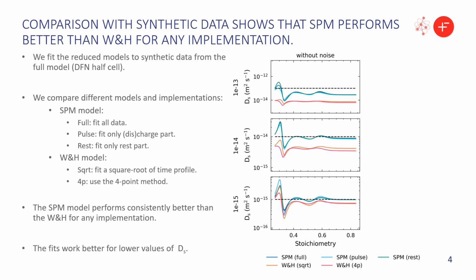In fact, we tried for different diffusion coefficients, and what we find here is that for larger diffusion coefficients, the models perform worse and worse. That was expected for the Weppner and Huggins because up here, when the diffusion coefficient is 10 to the minus 13, that extra assumption on the diffusive timescale is no longer satisfied, so we expect it not to work. For the SPM, the reason why it doesn't work is because the transient effects because of diffusion in the particles are comparable to the timescale of the diffusion in the electrolyte, and therefore we get some mixed up effects, and that's why the estimation is not so good.